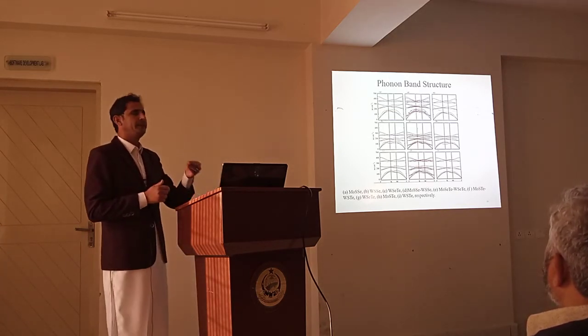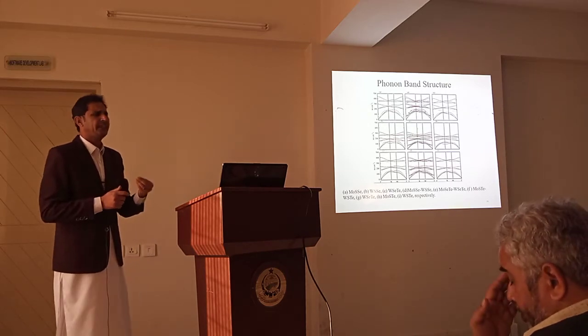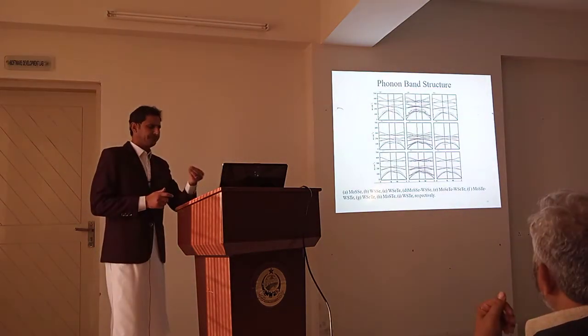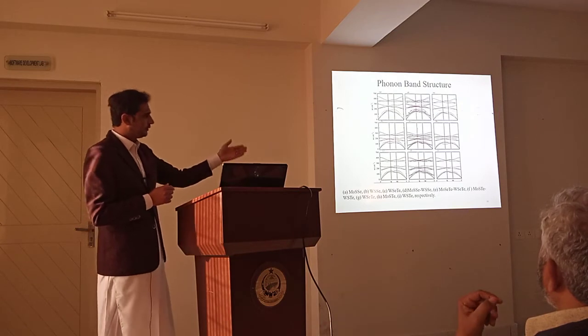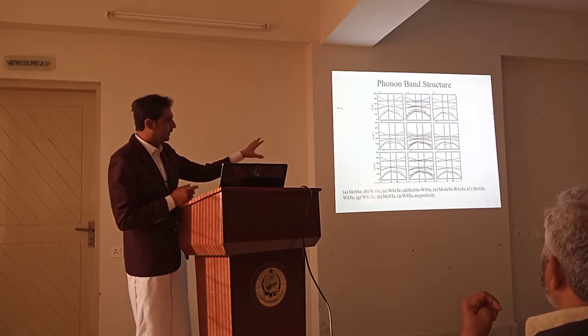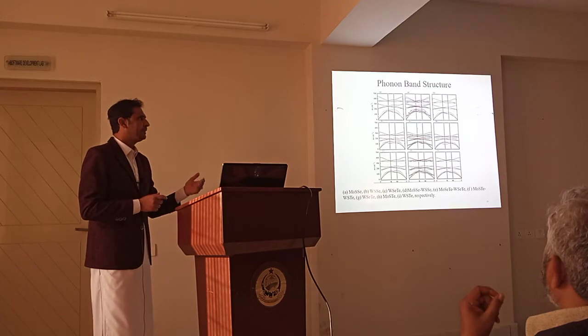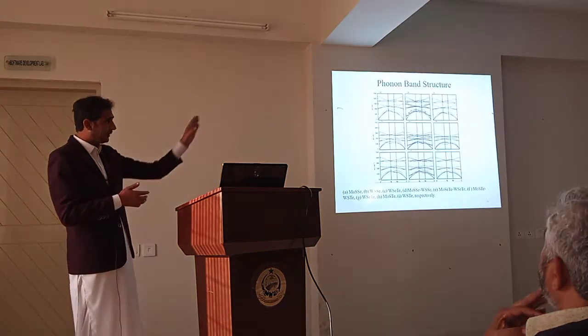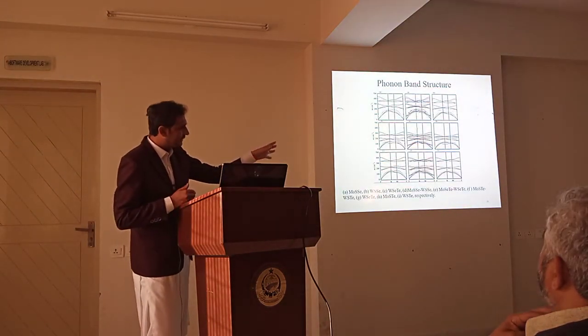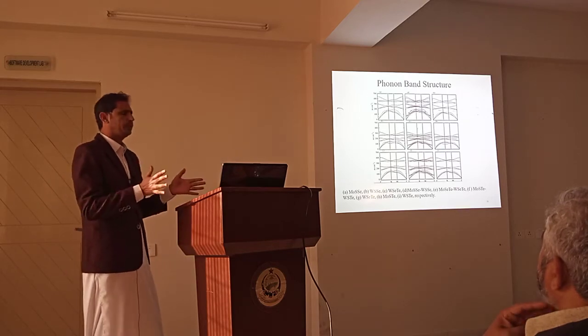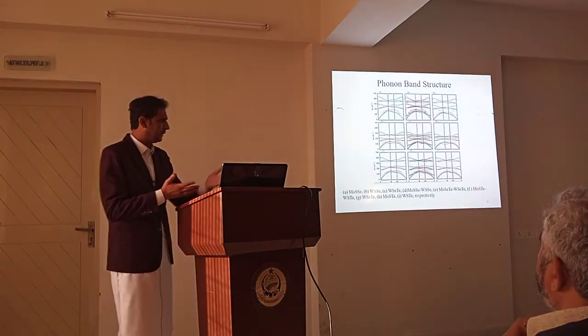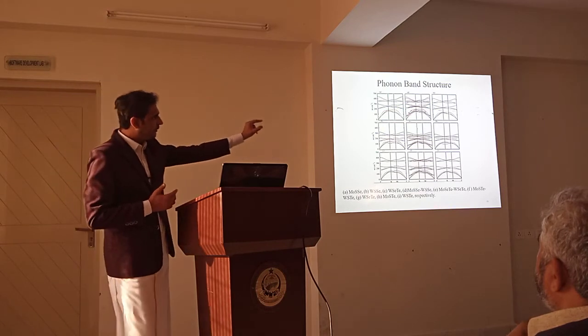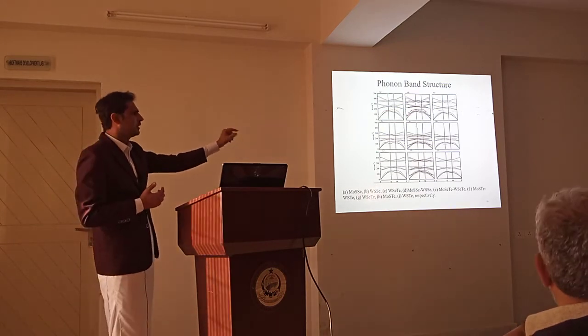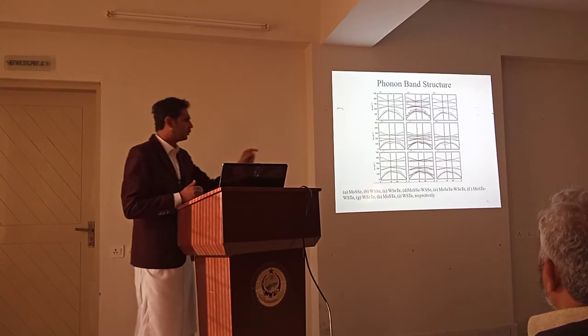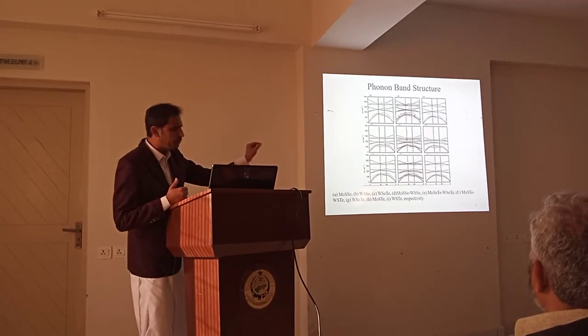When there is no imaginary phonon, meaning there is no imaginary frequency, then this system is experimentally possible. Now we can see that for all these figures, there is no negative frequency. It means that these monolayers, and also the mid one for the van der Waals structure, are experimentally possible. Now if we see the mid one, D, some other modes are also present above the acoustic branches. This mode is due to the van der Waals heterostructure.